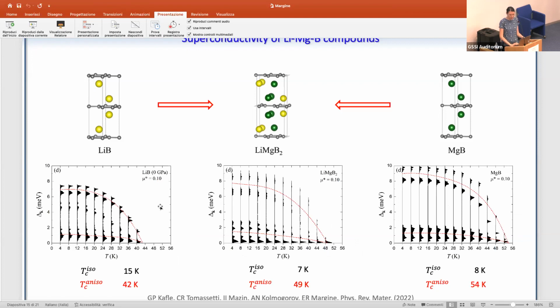If we look at the superconducting properties, we found again that with isotropic values for mu star 0.1, we find values of 7 Kelvin and 8 Kelvin. In fact, if you set mu star to 0.2 in the isotropic case, you are going to get 0 Kelvin. While in the anisotropic case, we find values of 49 Kelvin and 54 Kelvin respectively. So these values are much larger, about 7 to 8 times larger than the isotropic values. That's something I want to point out, that this may be important in this kind of layered materials. Of course, as I said, these systems are not stable, so they are very unlikely to be found experimentally.